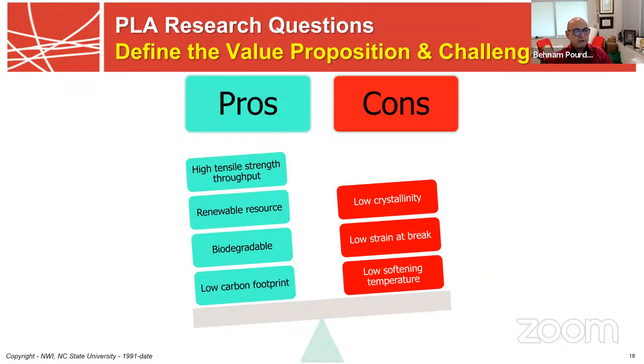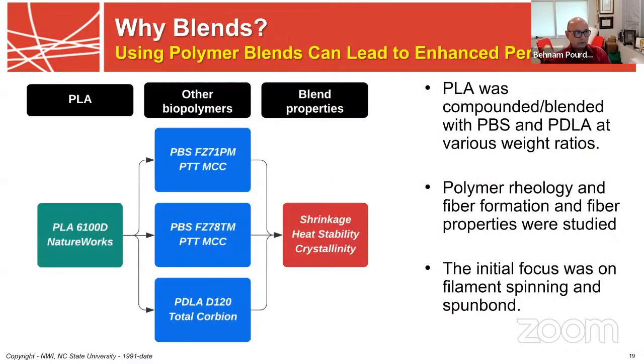So if you look at the challenges, PLA has low crystallinity. It's a pretty brittle material. It has low strain at break. It cold crystallizes. If it's not crystallized properly during the process, it continues to crystallize and it becomes even more brittle. It has a lower softening temperature. So this is your heat distortion temperature or heat deflection temperature. But in terms of the pros, it's got a pretty good tensile strength. It's a renewable resource. It's biodegradable. It is not home compostable. It is industrially compostable. And it also has a lower carbon footprint. So there are challenges that we have to face, and the work has been focusing on optimizing those challenges.